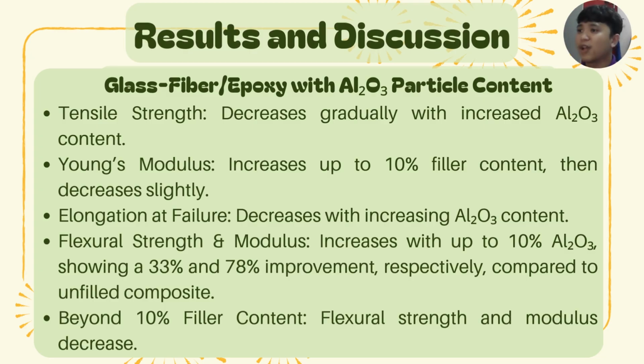Glass fiber epoxy with aluminum oxide particle contents. Tensile strength decreases gradually with increased aluminum oxide content. Young's modulus increases up to 10% filler content, then decreases slightly. Elongation at failure decreases with increasing aluminum oxide content. Flexural strength and modulus increase with up to 10% aluminum oxide, showing a 33% and 78% improvement, respectively, compared to the unfilled composite. Beyond 10% filler content, flexural strength and modulus decrease.